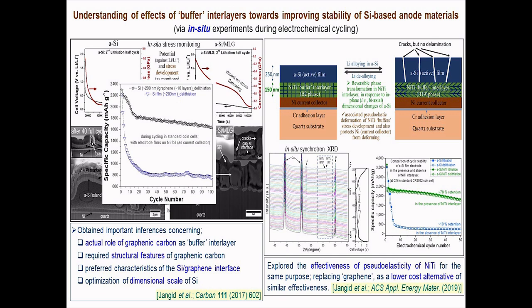So moving forward, we tried to see, instead of graphene, if one can use some material which can undergo pseudo-elastic deformation and accommodate a lot of strain reversibly upon extension and release. This is a well-known material, NiTi-based shape memory alloy, which is used for various applications, and we saw that it is also good for this application. And of course, we tried to understand why it is so.